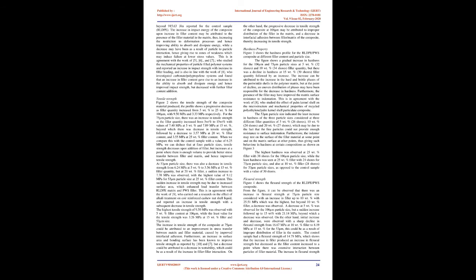This sudden increase in tensile strength may be due to increased surface area, which enhanced load transfer between RLDPE matrix and PWS filler. This is in agreement with the work of 9, who carried out a research on the effect of alkali treatment on coir reinforced cashew nut shell liquid, and reported an increase in tensile strength with a subsequent decrease in tensile strength. The highest tensile strength of 9.50 MPa was observed with 5 weight% filler content at 106 µm, while the least value for the tensile strength was 3.26 MPa at 15 weight% filler and 53 µm size.